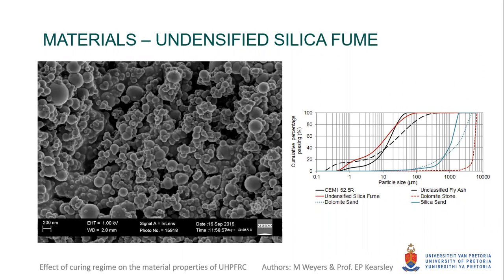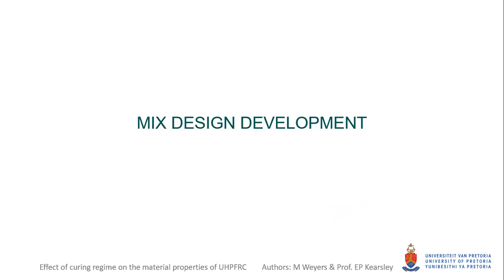Having a closer look at the undensified silica fume particles, with a scale of 200 nanometers, it is clear that agglomeration of the undensified silica fume particles is present. An optimum particle packing of granular ingredients of concrete is the key to a durable and sustainable concrete. It can result in a denser granular structure with enhanced mechanical properties and improved porosity.